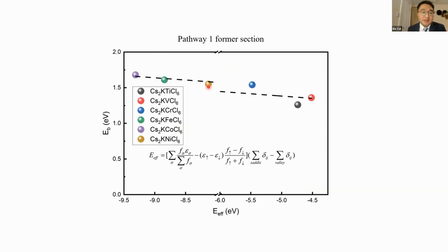We also calculate a family of double perovskites with different B sites. There is a linear scaling between our descriptor and migration barriers, similar to the d-band center theory, indicating that the theory is suitable for halide perovskite systems.